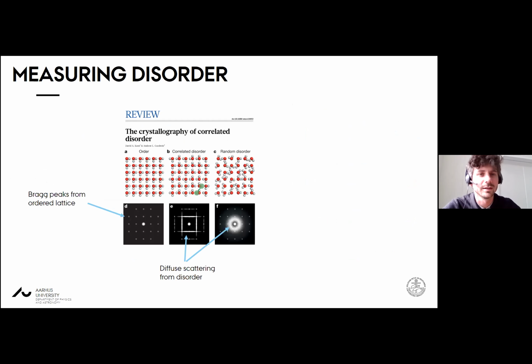There's an excellent review article, which is available in Nature, written from the point of view of neutron scattering, but it also applies to X-ray scattering, and that's the crystallography of correlated disorder. I really recommend everyone to read it. And the point I would like to make is that disorder in general is hard to see because in Bragg scattering, you can have these three cases where there's complete order, where this is water, and the oxygen and two hydrogens are forming a completely periodic structure and giving rise to the Bragg peaks. And now we have a case in B where the oxygens are allowed to rotate, but the motion is not completely disordered. So now oxygens prefer to form in certain preferred directions, but not necessarily with any long range order.